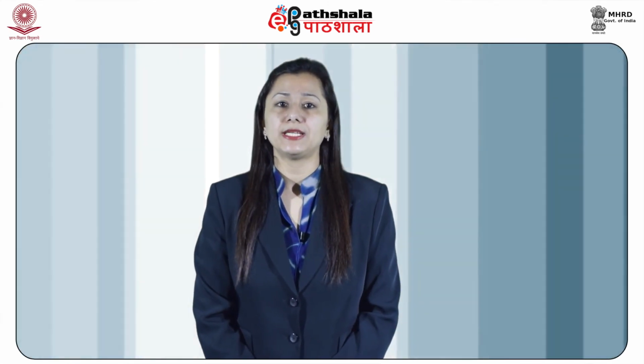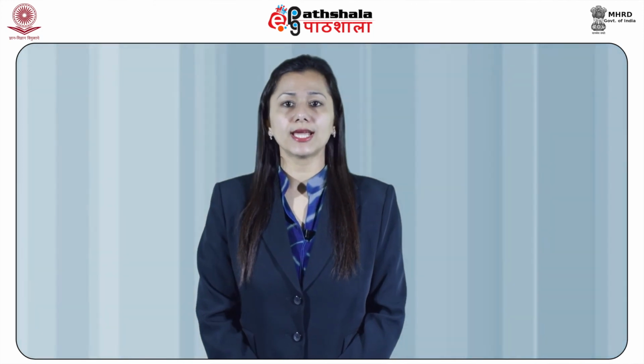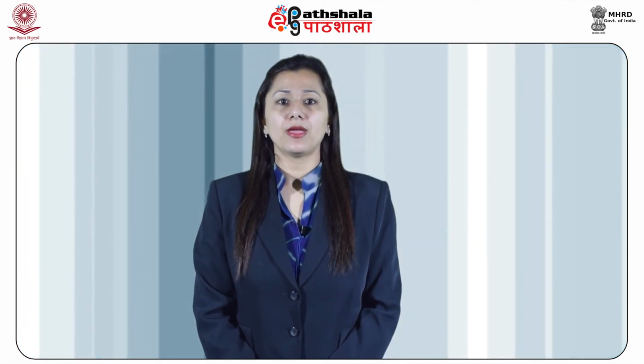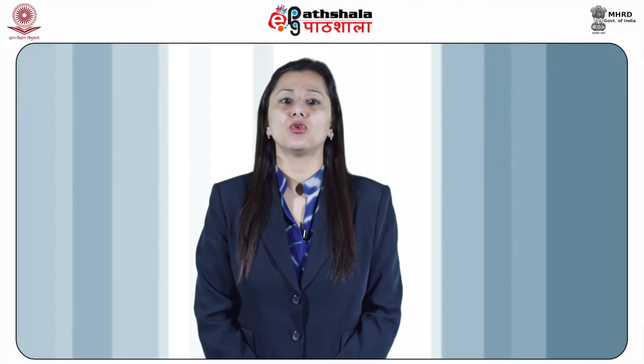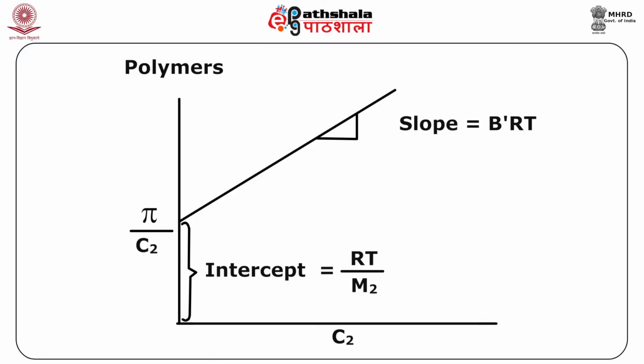The slope obtained from this graph is equal to the second virial coefficient B prime and its intercept is equal to the reciprocal of the molar mass M2 of the solute. Figure shows the plot of pi by C2, that is the reduced osmotic pressure, versus C2.